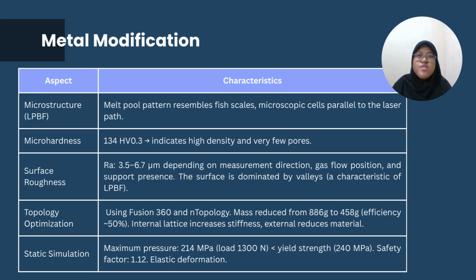Okay, this table shows some important aspects of the result of metal modification using the LPBF process. The first is microstructure. The melt pool pattern resembles fish scale with microscopic cell alignment with the laser path. Number two is microhardness, 134 HV0.3, indicating high density and very few pores. Number three is surface roughness, Ra ranging from 3.5 until 6.7 micrometers depending on the measurement direction and gas flow position. The surface is dominated by valleys.